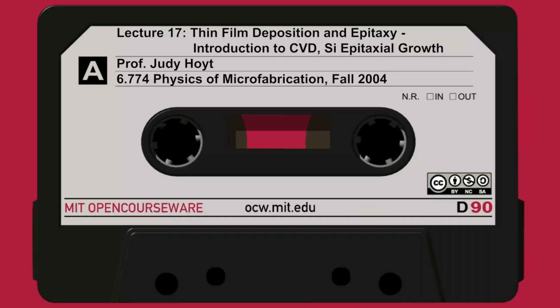So you see in an LPCVD process, which usually works at around a few hundred millitorr, you can stack a lot of wafers close to each other. You still have to worry about gas depletion in LPCVD. So what people do, assuming the gases are coming in here and going out, say going from left to right, is again tilt the profile of the temperature in the furnace.